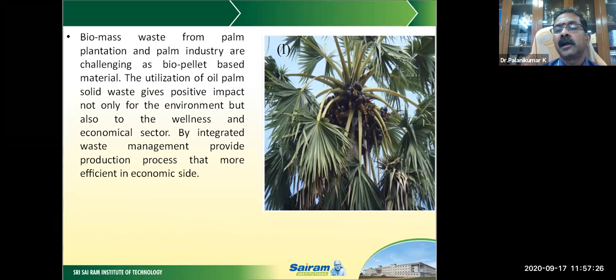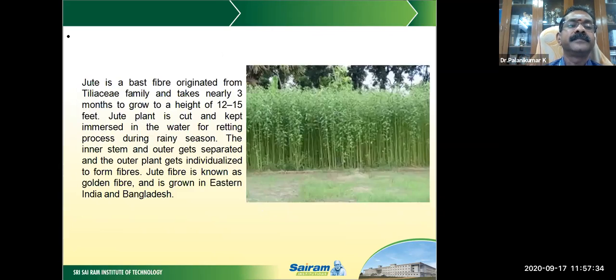So when we are talking about the economic side, normally the palm fibers are used for making many components. Jute is another fiber originated from the Tiliaceae family and takes nearly 3 months to grow to a height of 12 to 15 feet. The jute plant is cut and kept immersed in water for the retting process during the rainy season. Using this retting process only, we are able to get the fiber. So the retting process is also very important. The inner stem and the outer get separated and the outer plant gets individualized to form fiber. Jute fiber is known as golden fiber and is grown in eastern India and Bangladesh.